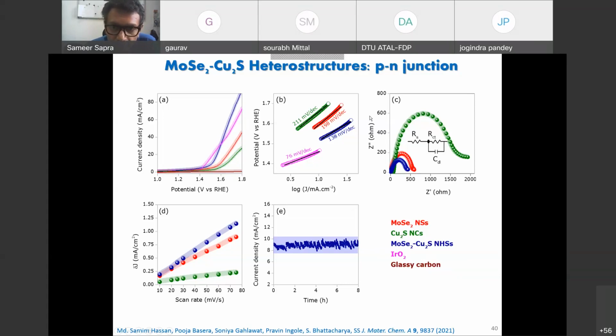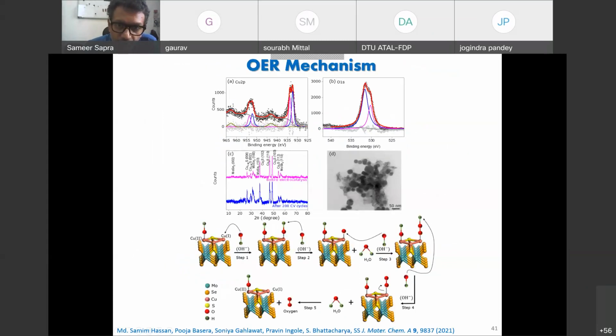So again, the Tafel plots show that these are pretty decent materials, resistivity data. Okay, again, the stability. Now we've also done stability tests for 24 hours. It continues as a very efficient catalyst. But the only thing that happens when you do this catalysis and then you again record the X-ray photoemission, you see copper gets oxidized. So if you remember, copper had only one peak. Now it gets oxidized into copper 1 and copper 2. Okay. But the XRD does not change. XRD remains the same, which means our material has not changed, but on the surface, since X-ray photoemission is a surface phenomenon, on the surface, things have changed. And what is that? Copper 1 and copper 2. So earlier I had only copper 1, and now I also have some amount of copper 2. Well, almost similar amount of copper 2.